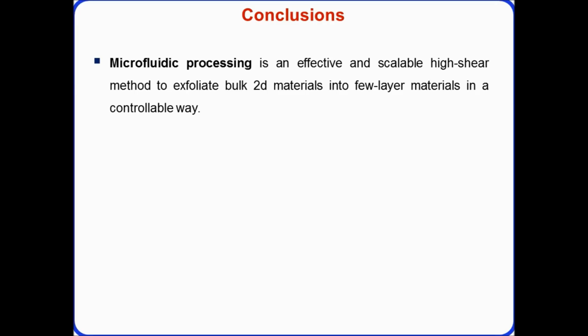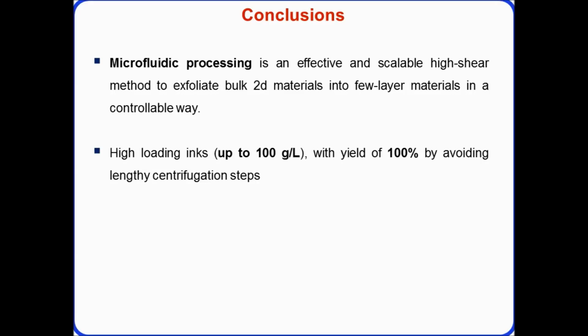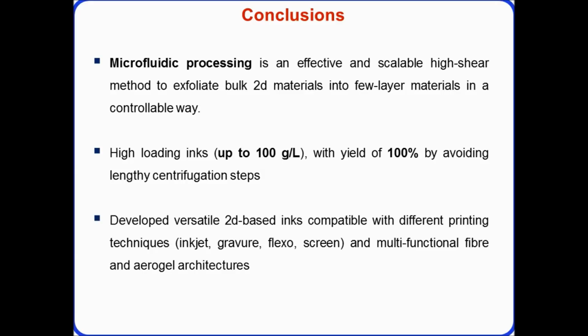In conclusion, microfluidic processing is an effective and scalable high shear method to exfoliate not just graphene but many bulk 2D materials into few layer materials, and we can do that now in a very controllable way. The benefit of the process is it's very uniform. We can achieve very high loading inks, up to around 100 grams per liter concentration, much higher than with other graphene production techniques, and we can have a yield of 100%. So we can avoid some of the other lengthy separation steps that I didn't discuss today. Essentially we can develop versatile inks compatible with different printing processes, and also create other functional architectures like the fibers and aerogel sponge architectures that I showed, which can have application in many other areas.